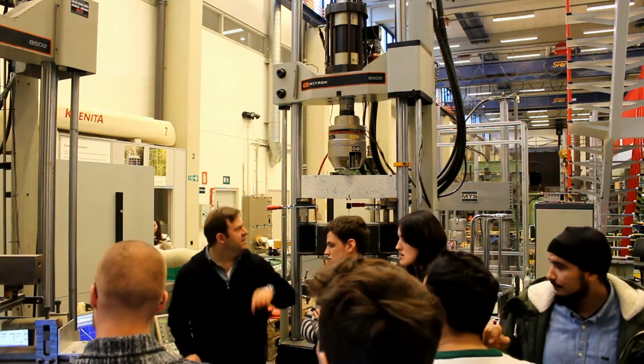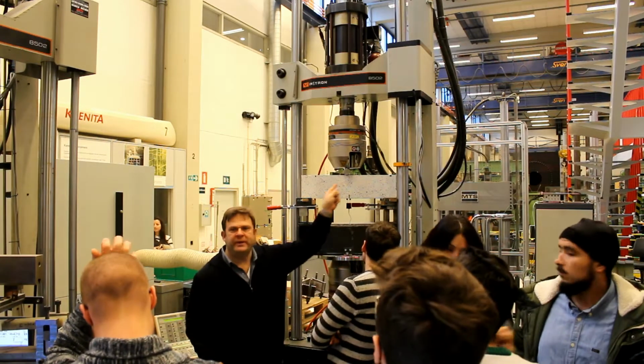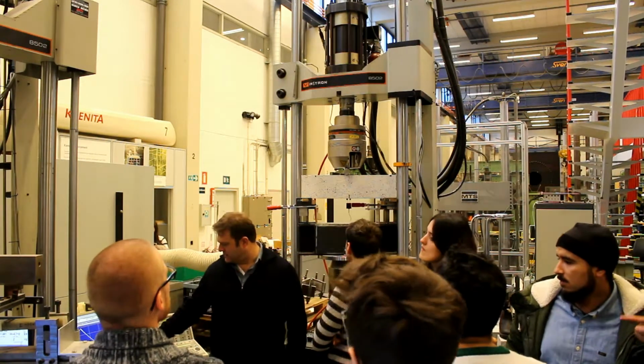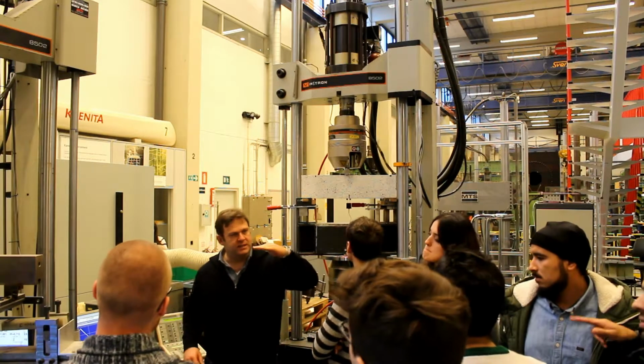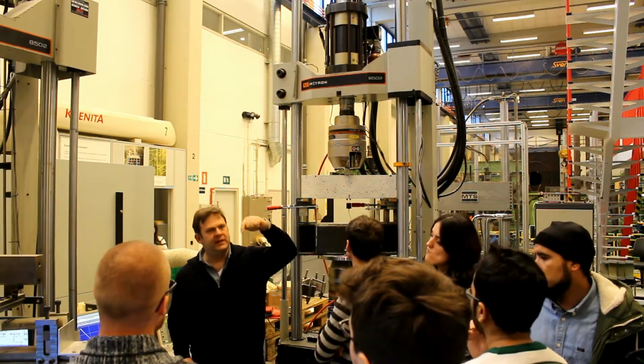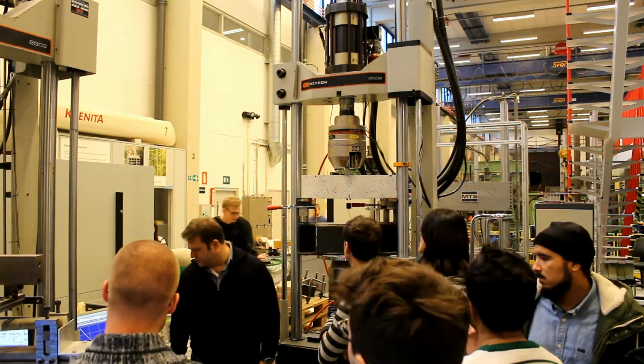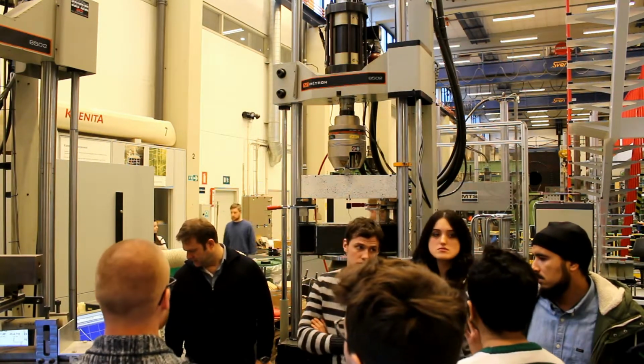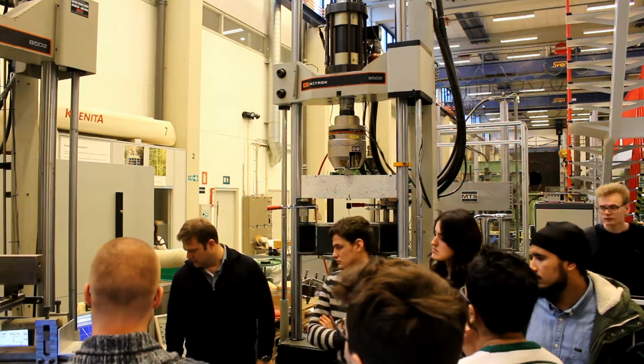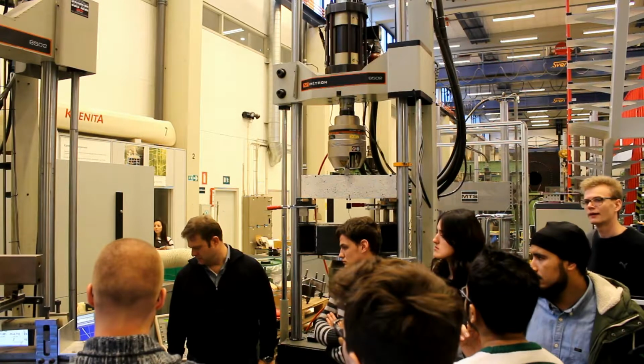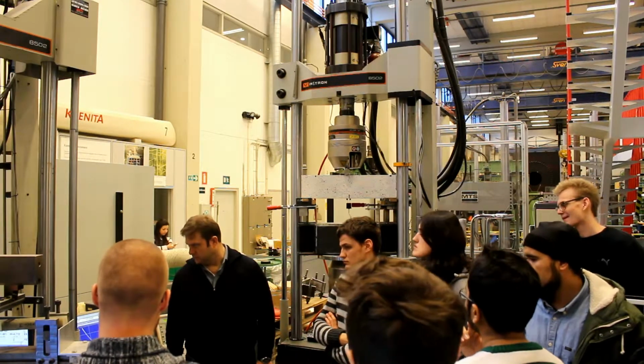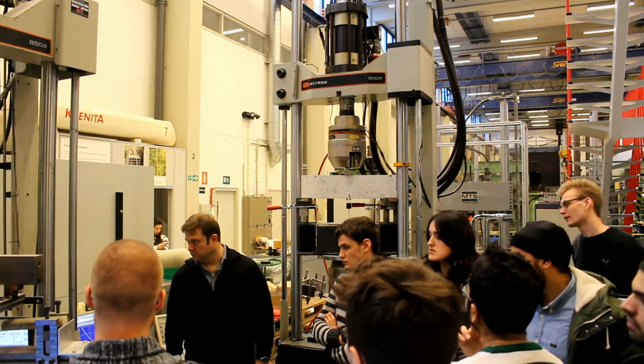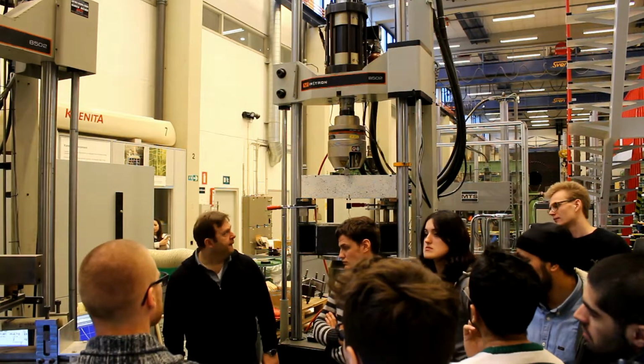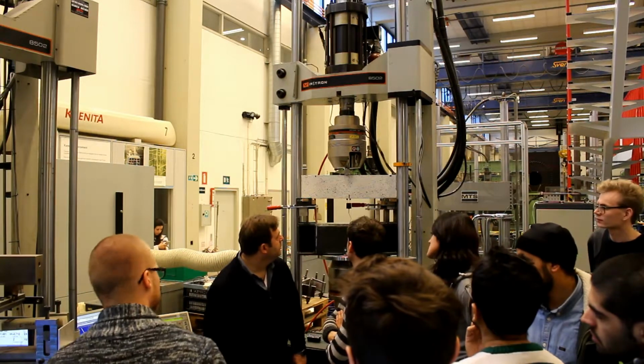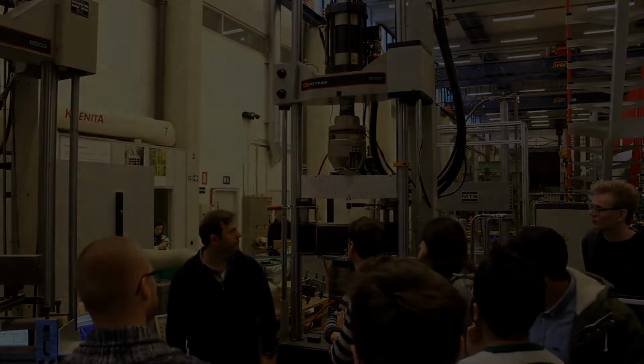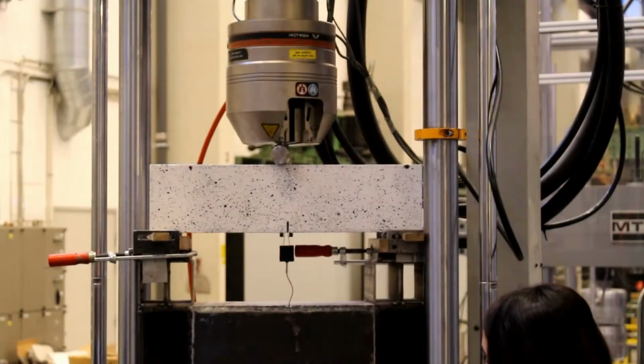Now there is probably a small crack starting to propagate at the notch. And once this line here reaches a zero slope, typically we get a crack. So we can observe that here. It's no more linear right now. Okay, so now we have a crack.